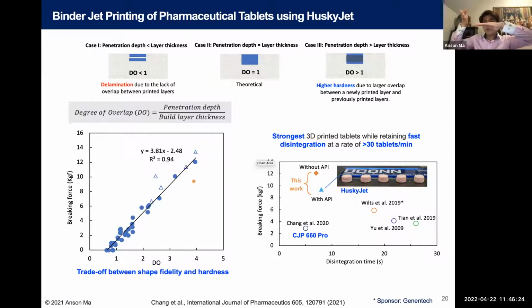Let's say the blue color here indicates the thickness of how much binder is wetting the powder bed. Imagine that if it doesn't wet too much, and then you spread a lot of powder on top, then when you print the second layer, there would be a disconnect between the first layer and the second layer. And this sample is going to be very weak. It tends to delaminate. Theoretically, you can have case 2, meaning that the thickness of the penetration is comparable to how much powder you roll on top before you print the second layer. And in case 3, basically you can tune this. I call this degree of overlap.